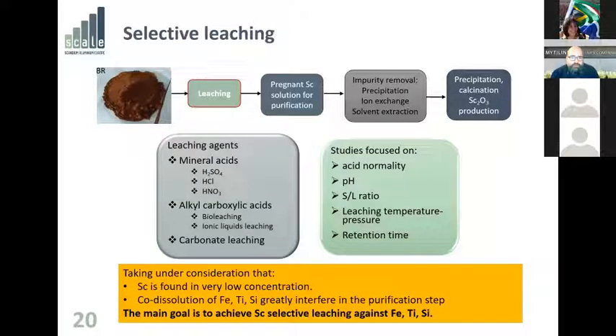So the idea is you go for leaching, you get a pregnant solution, which you need to go then to for impurity removal, which could be precipitation or ion exchange or solvent extraction. And then you get a precipitate, which you calcine and produce a crude scandium oxide. Now you can use various leaching agents. Most known, of course, is the mineral acids like sulfuric acid, hydrochloric, and nitric acid.